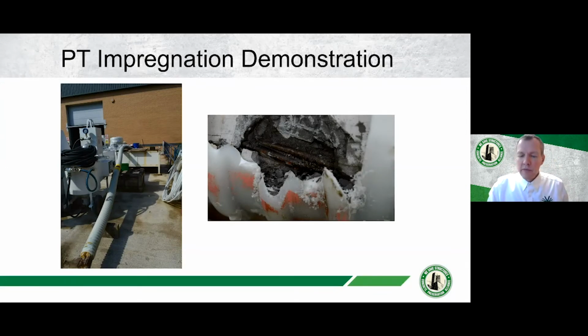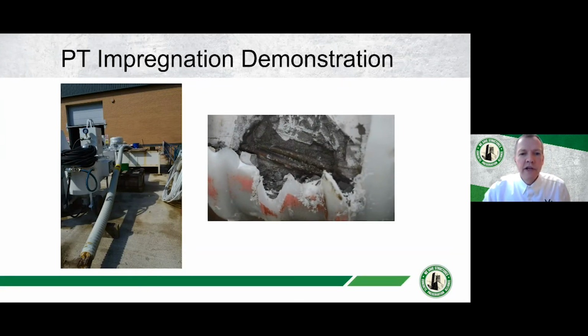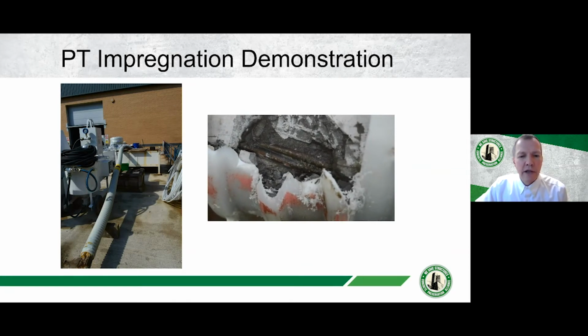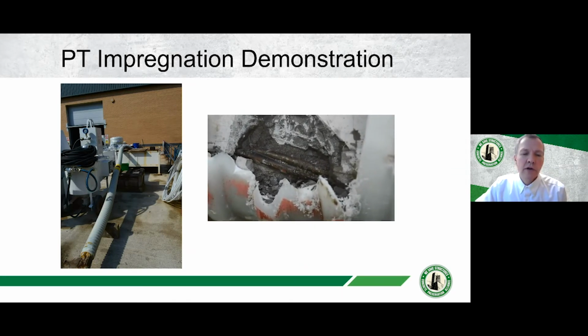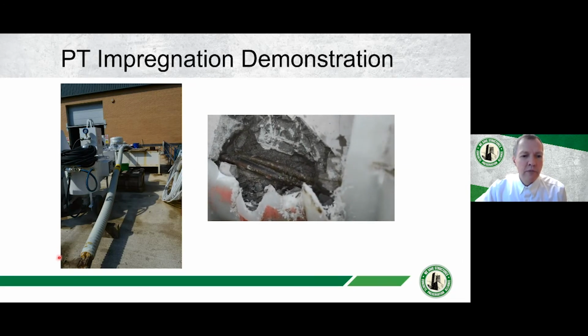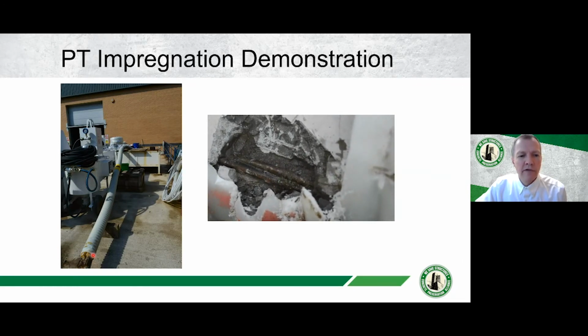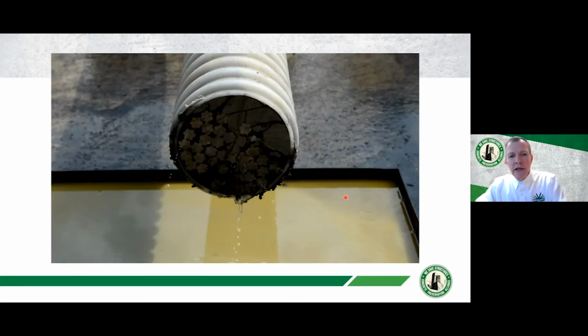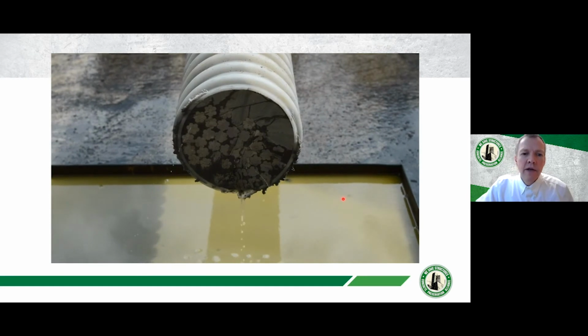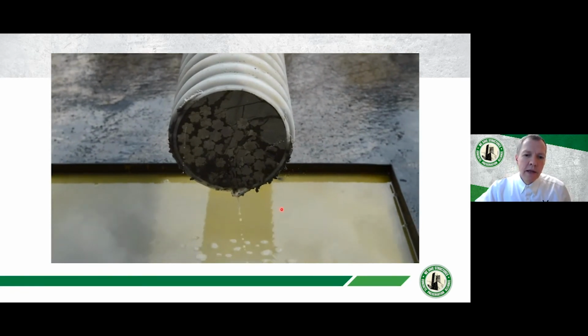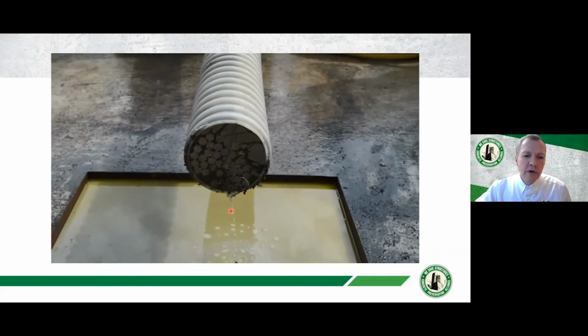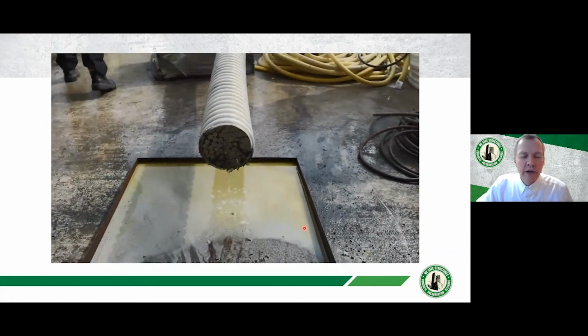In this picture here, this is a video from a demo that was done in the UK. A grouting contractor or a PT contractor there had built a mock-up, a tendon mock-up for a grouting verification, and then we used that mock-up for doing impregnation. You can see that the material, this is an opening that was somewhere along the length. The material was seeping out from between the wires, and at the end of the tendon, you can see that the material is coming out the end and dripping down and squirting out a little bit here.